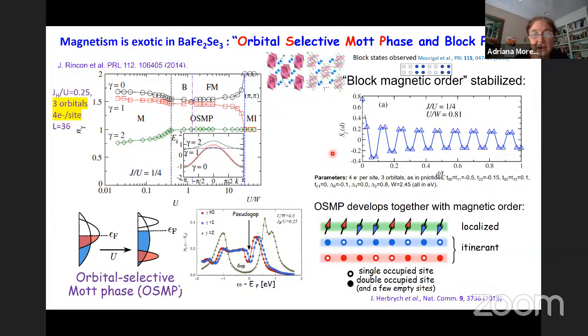This behavior arises from the localized spins, the spins of the electrons that are in the Mott-split orbital. So we propose that the block state observed by Mourigal et al. could be a manifestation of an orbital selective Mott phase. Experimentally, we still don't know.